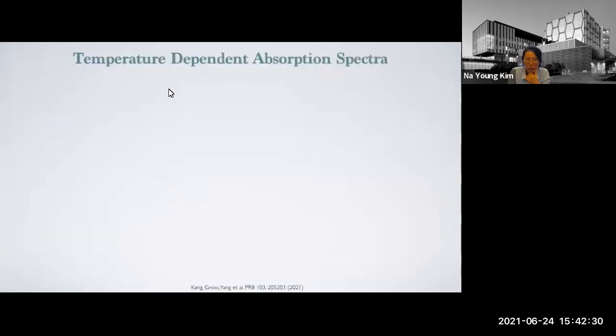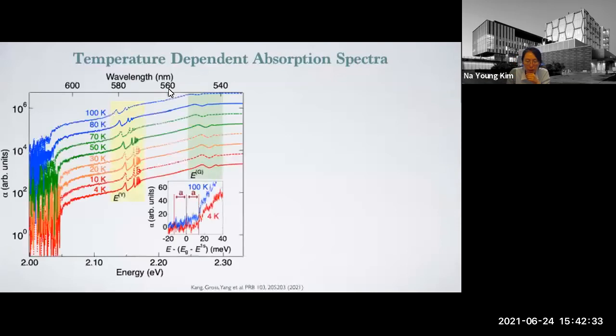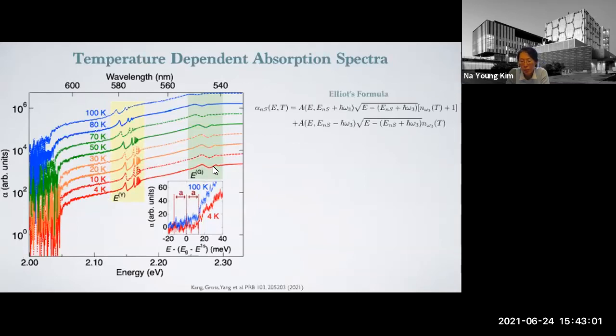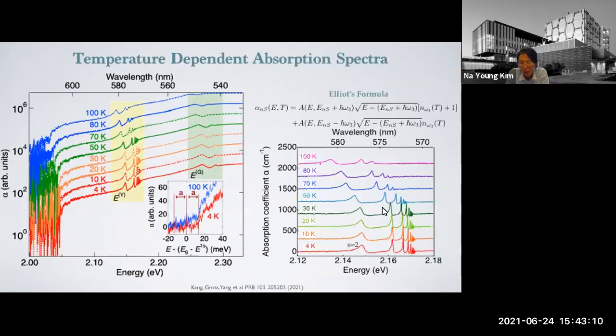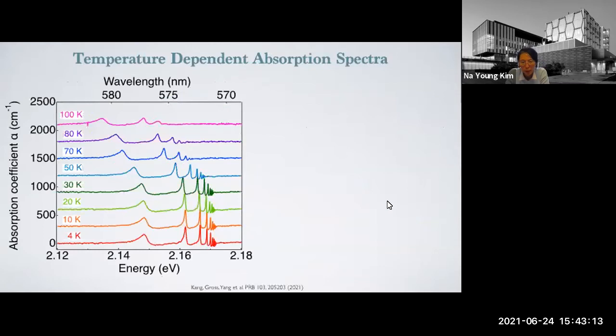Let's see the temperature-dependent absorption spectra. So this is the spectra at the different temperatures. You see there's a phonon background, and there are 2 groups of sharp peaks, which we call the yellow exciton and the green exciton. In this talk, I'm focusing on the yellow. The phonon background is described by the well-known Elliott's formula, basically square root of energy. So we can subtract the phonon background, and then what we are left with is a beautiful series of sharp peaks. Let's take a look at that.